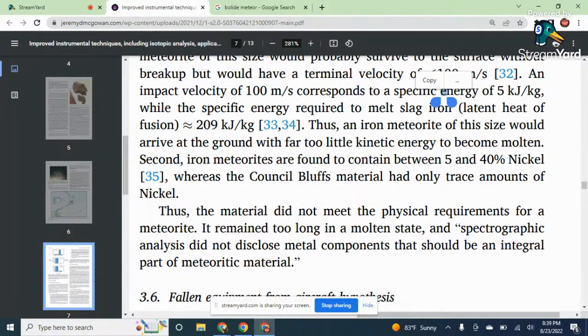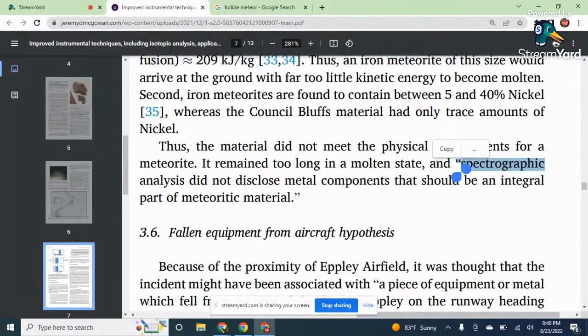So it had very little nickel when they analyzed it, which is a metal, and iron meteorites have about 5 to 40%, so a lot more. Thus, the material did not meet the physical requirements for a meteorite. It remained too long in a molten state, and spectrographic analysis did not disclose metal components that should be an integral part of the